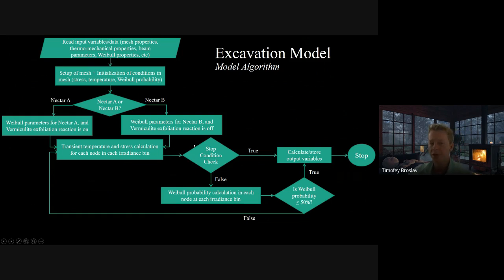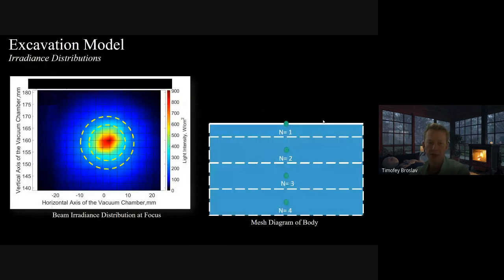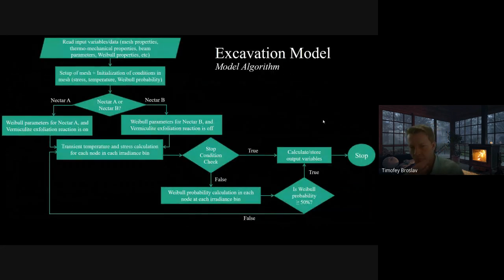And then stop conditions were checked depending on if significant melting had occurred or if a significant amount of material has been heated. And then the calculation was either redone or this was stopped, and certain variables were calculated and stored as outputs. And these are the ones that I showed in the table earlier.